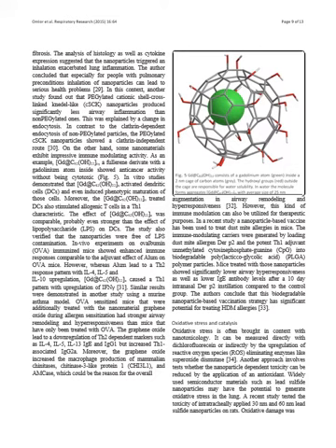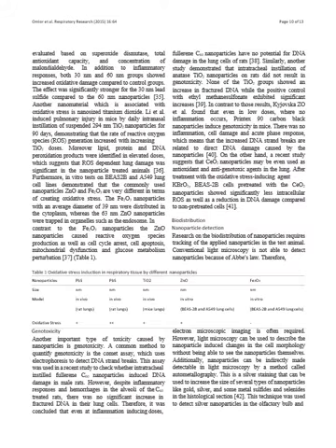Oxidative damage was evaluated based on superoxide dismutase, total antioxidant capacity and concentration of malondialdehyde. In addition to inflammatory responses, both 30 nanometer and 60 nanometer groups showed increased oxidative damage compared to control groups. The effect was significantly stronger for the 30 nanometer lead sulfide compared to the 60 nanometer nanoparticles.